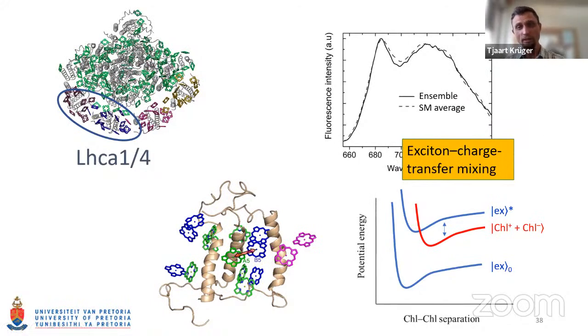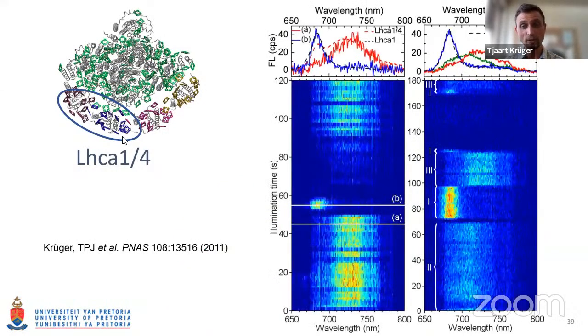Okay, so what do we see when we put one such system under the single molecule microscope? Okay, this is what we observed. So most of the time the system would reside in this redshifted state, but occasionally it would switch off the red emission completely. So temporarily, a photosystem 1 system would behave like a photosystem 2 system. And what I've showed you a few slides ago is that temporarily, occasionally, a photosystem 2 system can behave like a photosystem 1 system. Okay, very interesting.